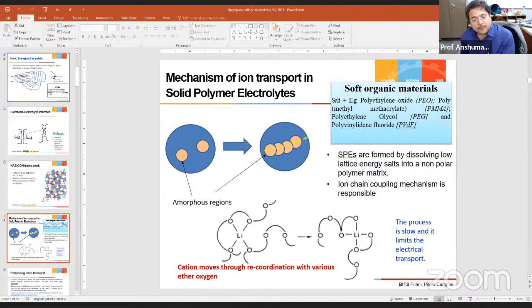What happens here? You have a polymer, then there are certain amorphous regions in the polymer. If you keep on adding salt, then these amorphous regions increase. Either their number will increase or their volume will increase, and there will be a connectivity in the amorphous regions. And finally, the ion-chain coupling mechanism leads to the ionic transport here. So lithium ion or sodium ion based polymers are there, but the conductivity is limited because of the coupling mechanism. Lithium ion has to couple with the chains, and this coupling doesn't provide fast ionic transport. So you have to break the coupling and do some kind of engineering inside this material so that these lithium ions can move freely like in tunnels inside the polymer, and the polymer will be able to provide a good interface.